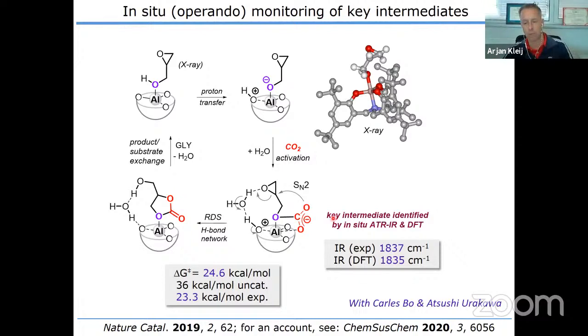The interesting thing is that we were able to see this intermediate. This is a key intermediate where we have that carbonate attacking that epoxide. By IR, we saw a peak at 1837, and by computation we could actually confirm that that indeed is this species. And we also know that for the catalytic reaction, experimentally we find a barrier of 23.3, and by computation we see that this barrier is actually nicely reproducible by DFT.